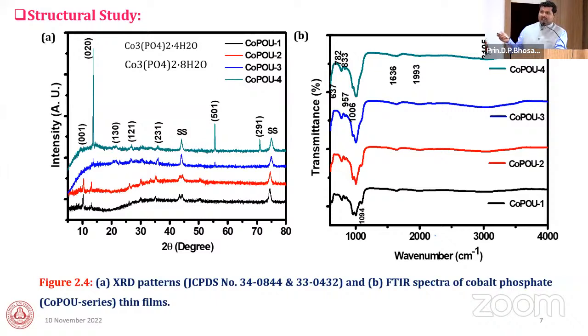It means the morphology is oriented growth. And also the interesting thing is that the cobalt phosphate, Co3(PO4)2 4H2O, is the first phase, and with increasing urea concentration, the phase changed to 8H2O. It means the hydrous content of cobalt phosphate is increased with increasing urea concentration.